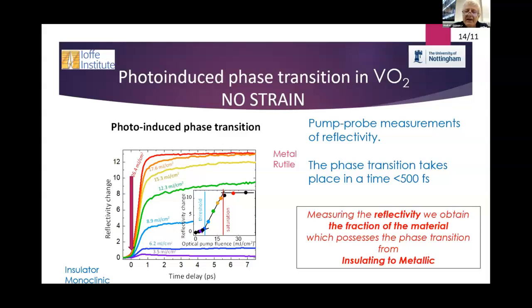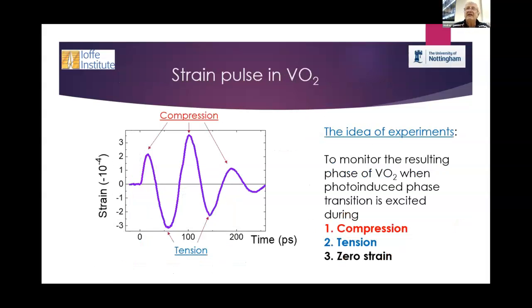So the main thing is that by measuring the reflectivity, we obtain the fraction of material which has undergone phase transition, from insulating to metallic, from monoclinic to rutile phase. So we see how phase transition takes place during the strain pulse, when coherent phonons are coming. This is the time evolution of strain which we measured exactly in the vanadium dioxide film. I shall not go into details, it's a bit more boring how to measure all this.